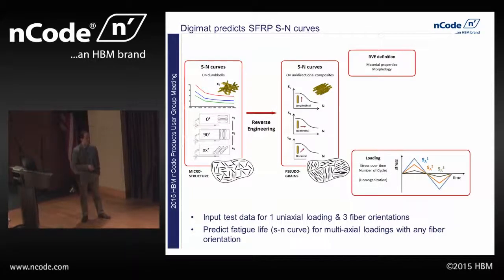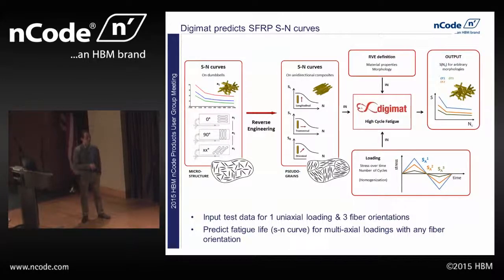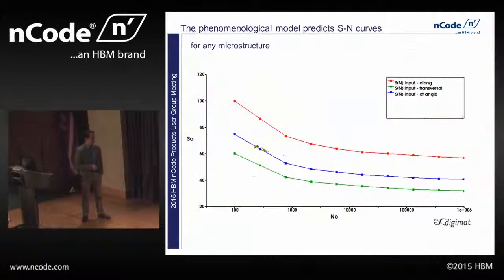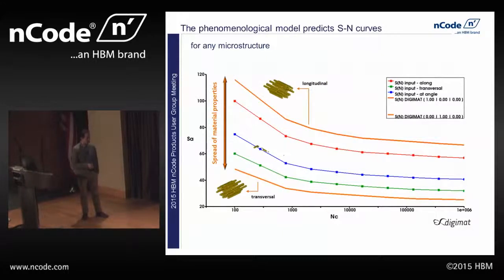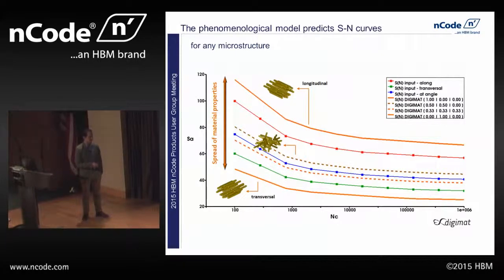We can then come in and change the loading, change the local fiber orientation, and use that to predict what our new set of SN curves are going to be. So an example of that you see here, you've got basically our 3 pieces of input data. We're going to bring those into our reverse engineering tool, and out of those we're going to be able to predict, all right, what's the most durable scenario for this material given a fiber orientation and loading, and what's the least durable scenario for this material given a fiber orientation and loading. And then we can predict kind of any state in between there, like this here is a 2D random state. So if you had a weld line, that's what that would look like.